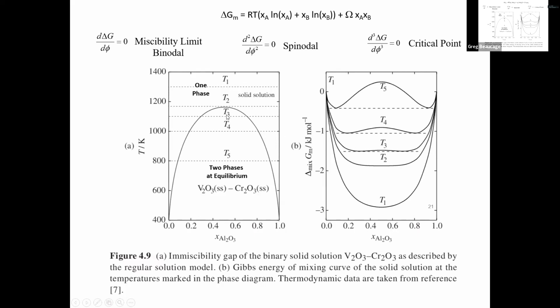So everybody wants to stay away from the critical point. It's an important point in the system, but it's not where you want to be because there's no way to predict what happens there. Say you're going to have diffusion, everything kind of stops. There's no driving force for diffusion, no concentration gradient that's going to happen. So it's called critical slowing down. As you approach the critical point, the transition stops happening, things slow down. And there's a bunch of other kind of bad words for critical points.